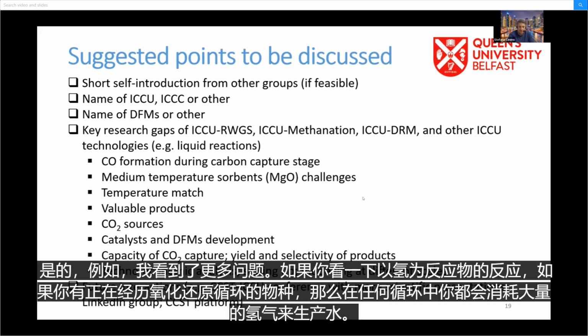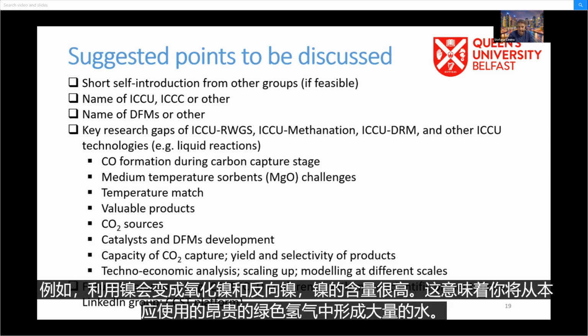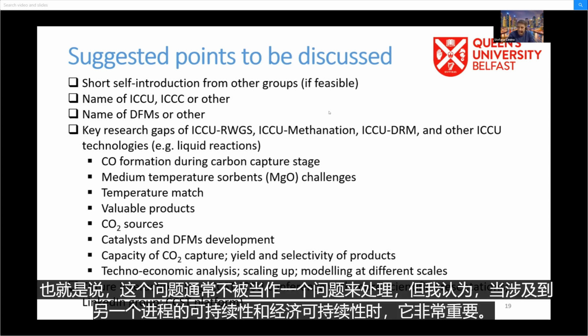Yeah, for example, I see more problems if you look at the reaction where you have hydrogen as a co-reactant. If you have species that are undergoing redox cycles, then you're going to consume a lot of hydrogen to produce water across any cycle. For example, with nickel that turns into nickel oxides and back to nickel, at high loading of nickel, you will form a lot of water out of the costly green hydrogen that you are supposing to use. That is something that is not commonly addressed as an issue, but I think it is very important when it comes to the sustainability and the economic sustainability of the process.